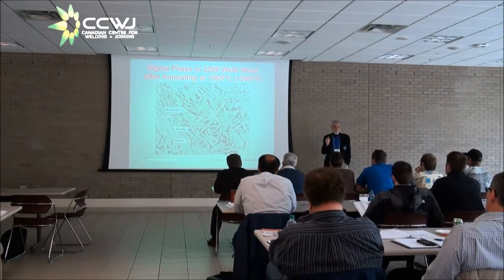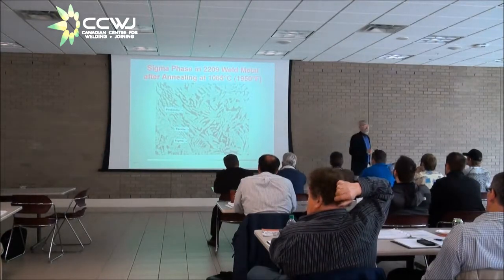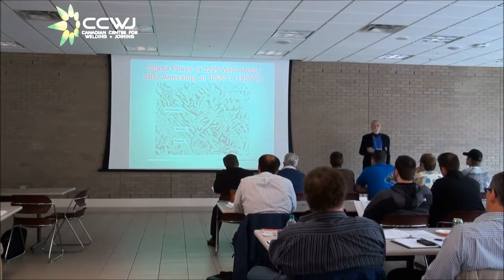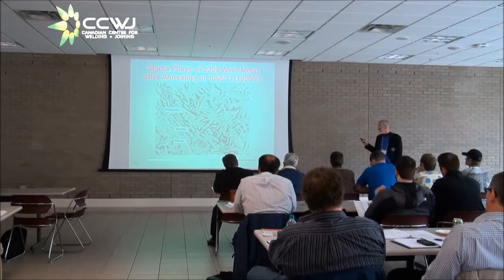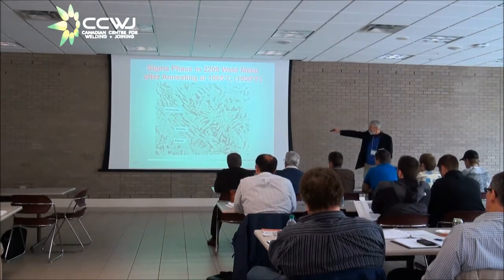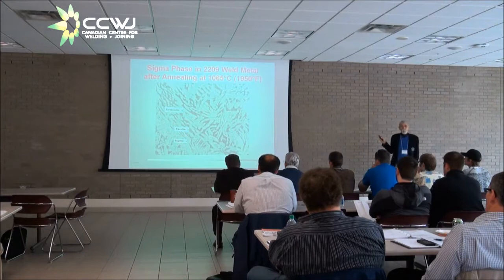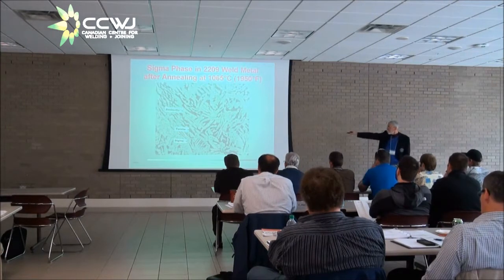3 joules. Full-size impact, not a subscale. 3 joules. Then we measured the tensile elongation, and it was about 10 or 12%. Then I looked at the microstructure, and here was the answer. All these white islands that are outlined but not touched, sigma phase. Pretty big hunks of sigma phase. Dark stuff, of course, that's the ferrite.